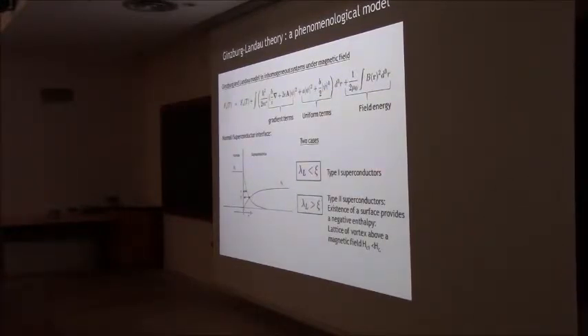If lambda is smaller than ξ, then you have a type 1 superconductor. It means that you don't gain energy by making an interface. But if you have lambda larger than ξ, every interface will provide a new gain of energy. It provides negative enthalpy to the system. Then in this kind of superconductor, when you apply magnetic field, the system wants to make as much interface as possible between normal and superconducting states. And how it does that, it lets some magnetic field go inside the superconductor, and this magnetic field is carried by what we call vortices.